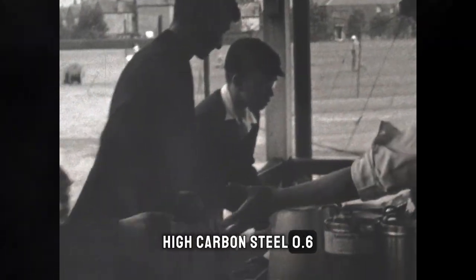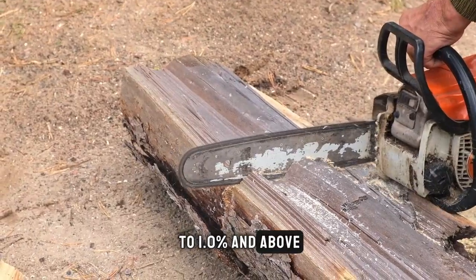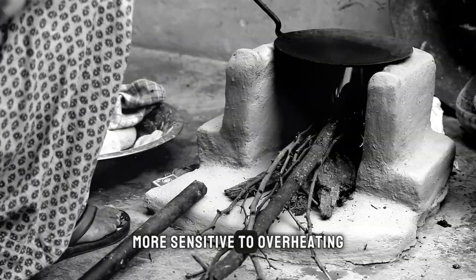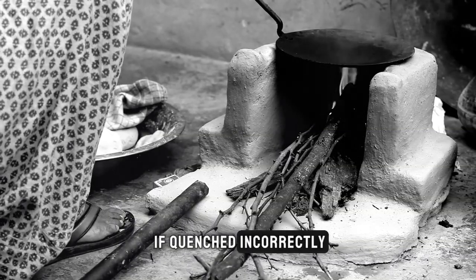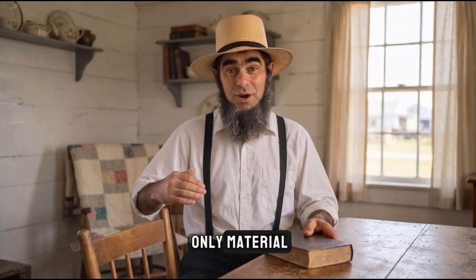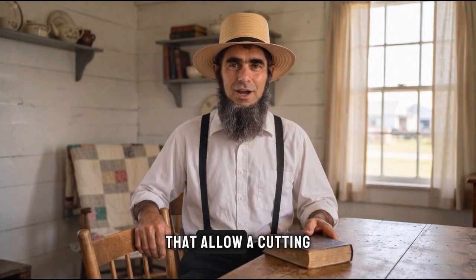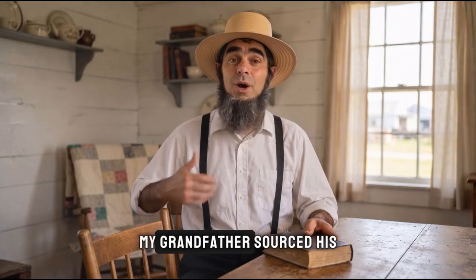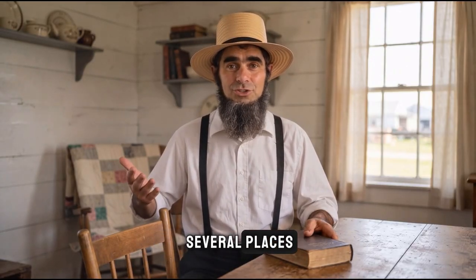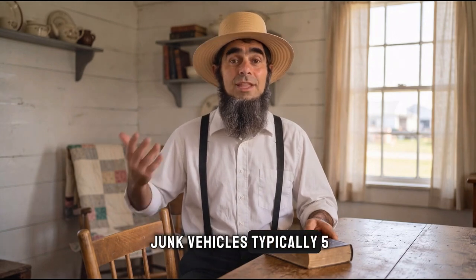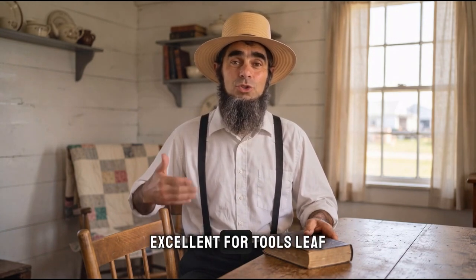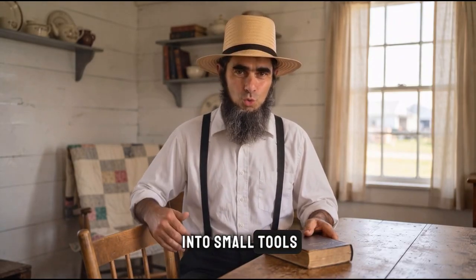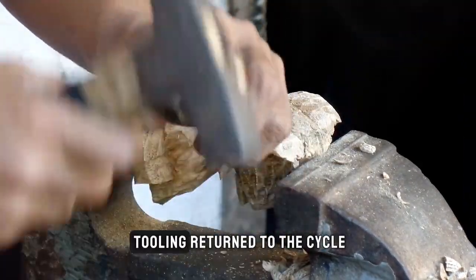High carbon steel, 0.6 to 1.0% and above, is what tools are made from. More sensitive to overheating, more likely to crack if quenched incorrectly. But it is the only material that can be hardened to the Rockwell values that allow a cutting edge to survive use. My grandfather sourced his high-carbon steel from several places. Old coil springs from junked vehicles, typically 5160 steel, excellent for tools. Leaf springs from trucks and farm equipment. Old files, which are high-carbon tool steel and can be reforged into small tools when worn past usefulness as files. Old chisels, punches, worn tooling returned to the cycle.